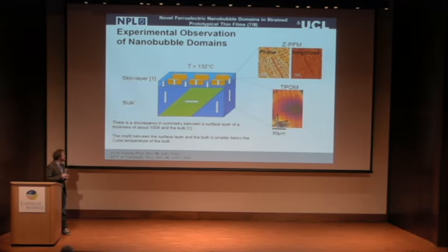Okay, so that's cool. Different. It's a very thin layer at the surface that we're actually imaging using the PFM. So then we wanted to check this, so we used transmission polarized optical microscopy and actually confirmed that the bulk of the crystal was ferroelastic AC domains. So these bubble domains that we're observing at the surface with PFM are distinctly a surface effect on a very thin film at the surface.